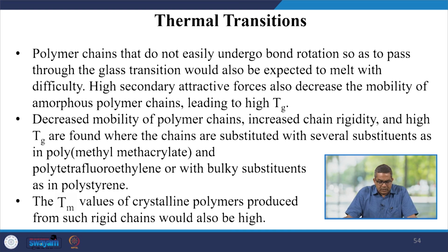Now, the polymer chains that do not easily undergo bond rotation so as to pass through a glass transition would also be expected to melt with difficulty. The high secondary attractive forces also decrease the mobility of the amorphous polymer chain. So, the movement of the chain is very important. Decreased mobility of the polymer chain increases the chain rigidity and gives a more compact structure and high glass transition temperature, and the Tm value of the crystalline polymer produced from such rigid chains would also be very high.